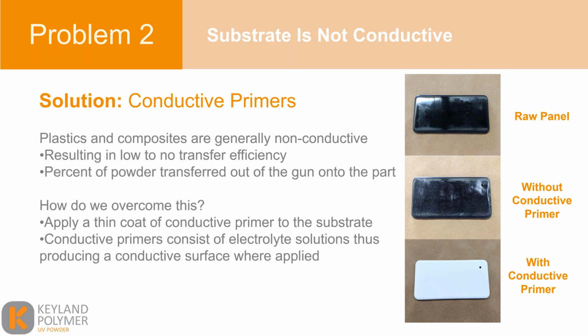However, conductive primers, which consist of an electrolyte solution in a liquid that is sprayed onto the part and then flashed off using heat or blown off with an air knife, will change the conductivity of the surface so the powder can adhere to it. And the bottom image is that same panel with a conductive primer applied and then flashed off right before coating and successfully coated with a white UV curable powder coating.